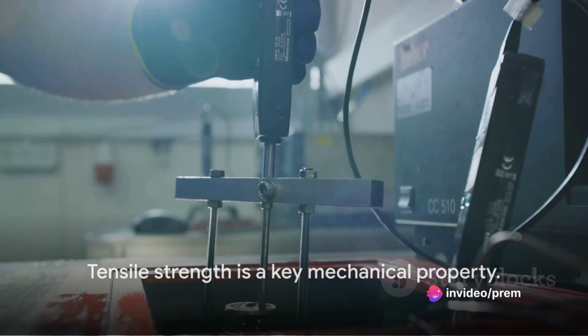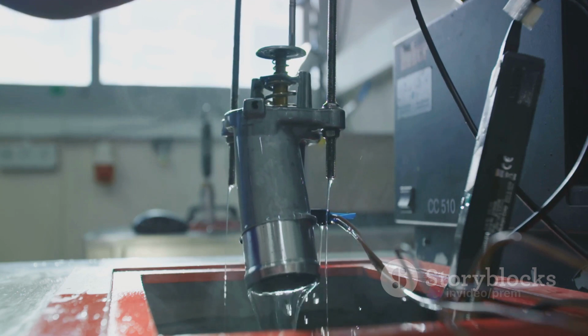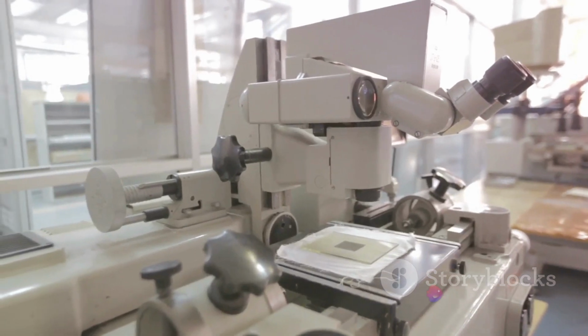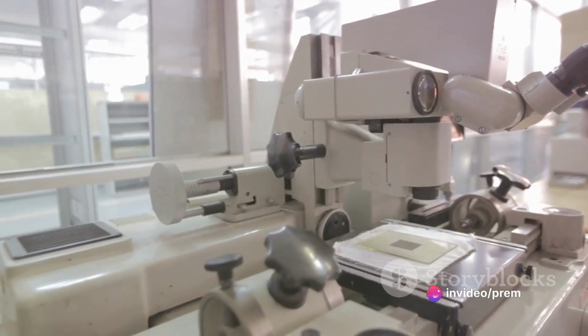Tensile strength is another key factor. Specimens are made as per ASTM E8 standard, and the ultimate tensile strength is evaluated using a HICO HLC 693-35 universal testing machine. Three specimens are tested for each composition to increase reliability in the experimental results.